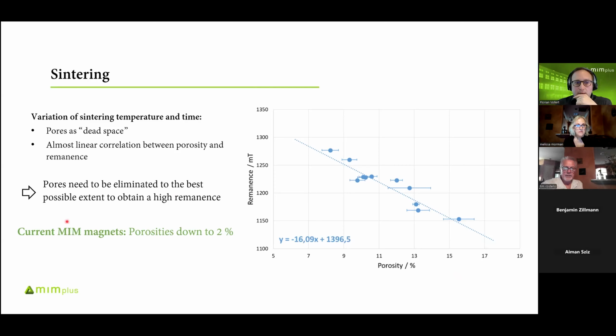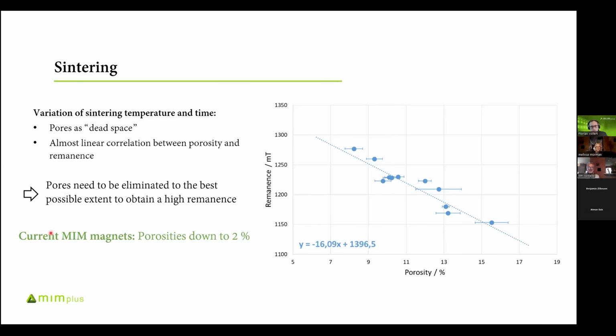So it's really crucial to eliminate the pores to the best possible extent to obtain a high remanence. And because you're injecting complex, three-dimensional shapes, there's a lot of science here of how you end up with your final net geometry. If you didn't care about tolerances, it would be one thing. You could smash and bake and do all kinds of stuff to eliminate this, but you're trying to hit an end tolerance on a three-dimensionally designed and toleranced part. So the science of that is really also a special sauce of MIMplus. And also now we are really able to achieve porosities down to 2%. This is also comparable to a press-sintered magnet.